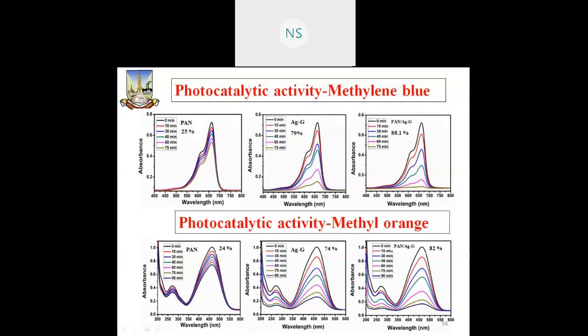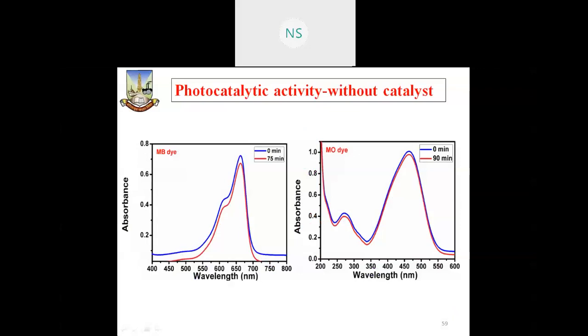Next is the methyl orange. Again, this material has good degradation ability, with methyl orange degrading 82% as compared to the methylene blue. Next. This is the photocatalytic activity without catalyst. Just look at the degradation activity of this material without catalyst: no degradation of methyl orange and methylene blue is taking place. We gave 0 to 75 minutes for methylene blue and methyl orange, but no degradation takes place.